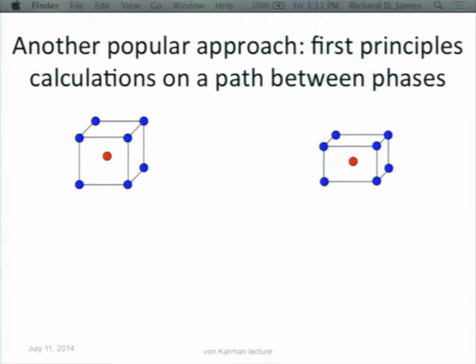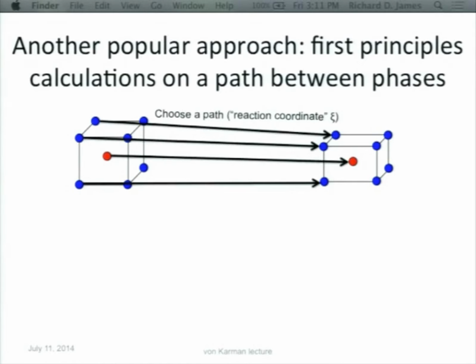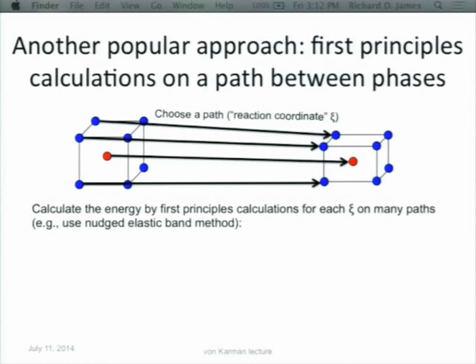Finally, I'll mention another approach. You imagine the unit cell of the austenite phase, and now you imagine a one-parameter family, a path between the austenite and, say, one of the variants of martensite. This is a very popular thing to do, and you compute using first principles calculations the potential energy along this path, and the parameter of this path is called a reaction coordinate.